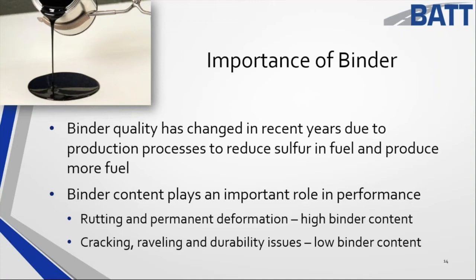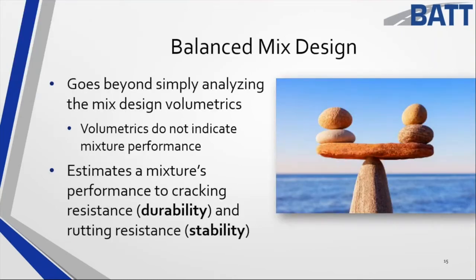Binder quality has changed. Binder plays an important role in performance. In its liquid form, binder is a lubricant — heat that roadway up and what do you have between the rocks? Oil. But if you take that binder and get the correct stiff grade, it moves from being a lubricant to a sticky resin type material that binds the structure together. If you cool it all the way down, you've got to be careful of what they call the glassy transition temperature, where the product can become brittle. It goes beyond analyzing volumetrics and helps us estimate performance.